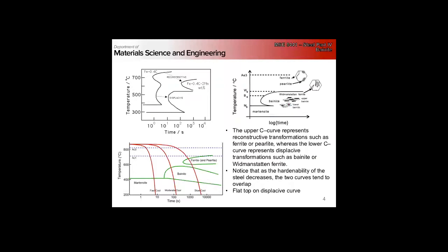But if we look at the isothermal TTT diagram, you see the relationship we just said, right? There's the Widmanstätten. A little bit lower is our Bainite start temperature. We go lower still, and we get to the martensite regime. But notice martensite is this flat line, right? So it's athermal. It takes basically no time to form martensite. Bainite is not athermal. It takes time. It has a measurable kinetics associated with it. So in that way, it's sort of like this hybrid in-between thing between Widmanstätten ferrite and